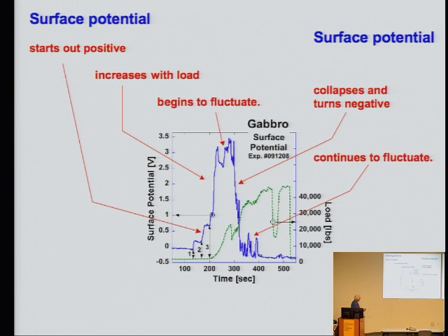So what we see here is that even the acceleration of the press, which goes up and brings the rock piece up, the rock, of course, sitting supported by the piston on one side and just another support on the other side, this acceleration already creates enough charge carriers to see a little bit of electric charge building up. There, at that point, the piston really makes contact, and the hydraulic press is kind of feeling, am I there? Maybe Gary also turned off the valve a little bit. So we get a little bit of voltage, about half a volt. Then as soon as the charge builds up on the rock, we are building up the battery voltage.